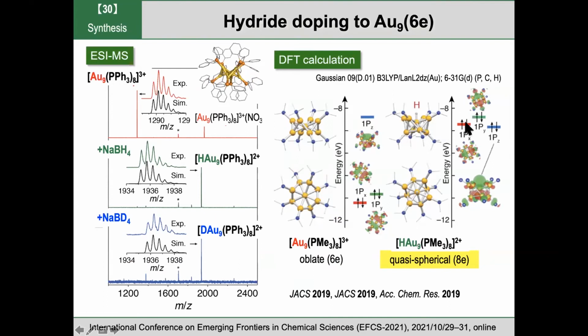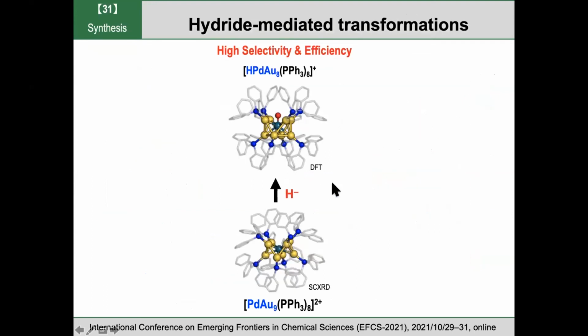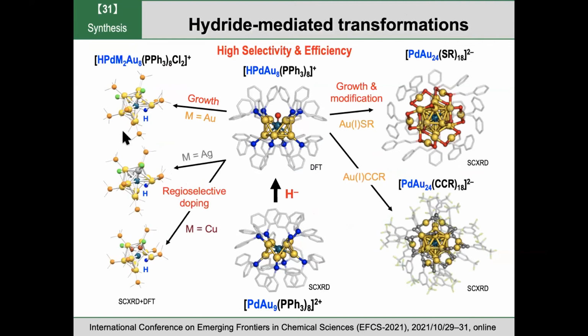And these hydride-doped species are very active for further reactions. After hydride doping, the cluster becomes very reactive, and then we can induce a variety of chemical reactions with high efficiency. We can also dope other elements. Regioselective doping is possible. And we can also change the whole set of ligands to different ones. And the efficiency is very large. So we believe this approach is very promising for targeted synthesis and large-scale synthesis of superatoms.